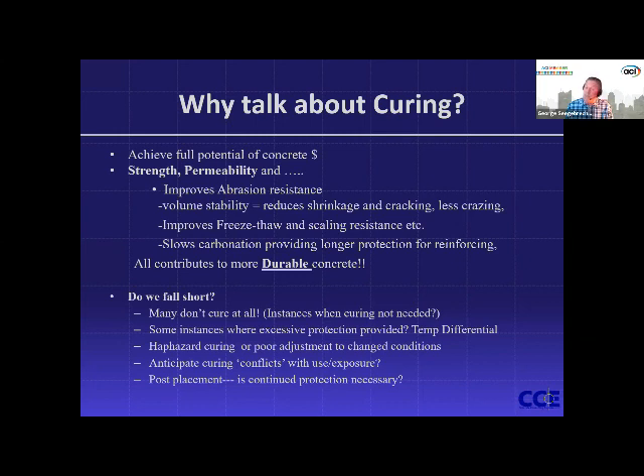Crazing generally is maybe due to lack of curing. If you delay the start of curing and you have a relatively rich mix, high rate of evaporation that day, you can get these polygonal shaped cracking patterns. Generally, they're not deep at all, but again, better curing would have you have less of that. Improves freeze-thaw durability and scaling resistance. I kind of put them in the same camp. It is always better with better curing.